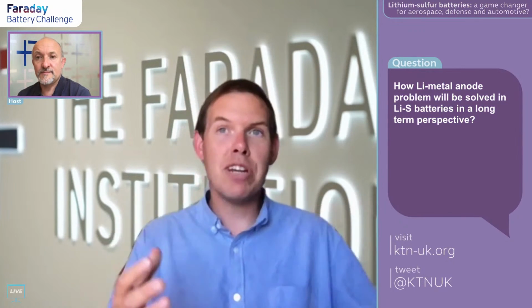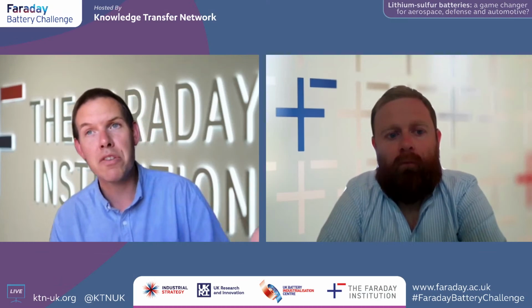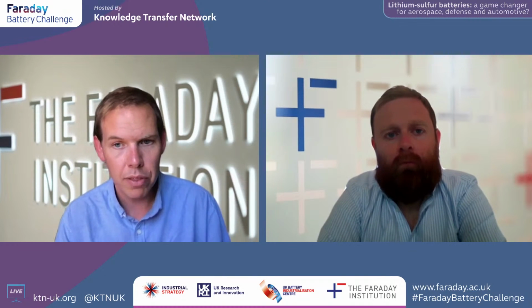So these are inherently unstable or maybe metastable materials, and engineering and designing solutions to make them more stable over long cycle lives is challenging. But what I do think that we've seen within the lithium-sulfur development is some very interesting proposals, particularly perhaps around electrolyte additives that can decompose into providing a very stable solid electrolyte interface at the anode, as well as a range of different solutions on making protected lithium metal anodes that I think are really exciting to pursue. And back to that comment about solid state batteries, obviously the SolBat program, which is another one of the Faraday Institution's large research programs that's been going now for a bit more than 2 years, have made great strides towards both making solid electrolytes, but also making protected metal anodes.